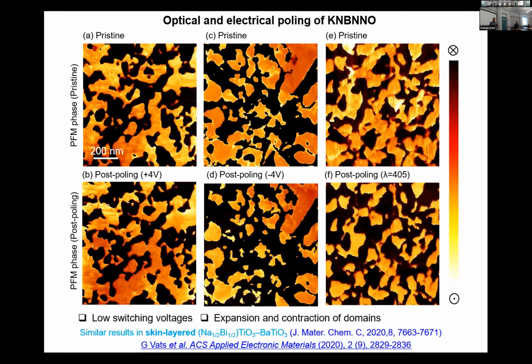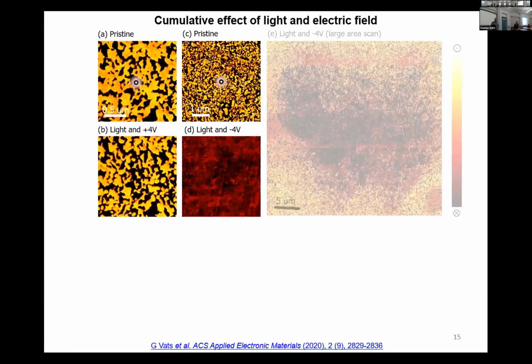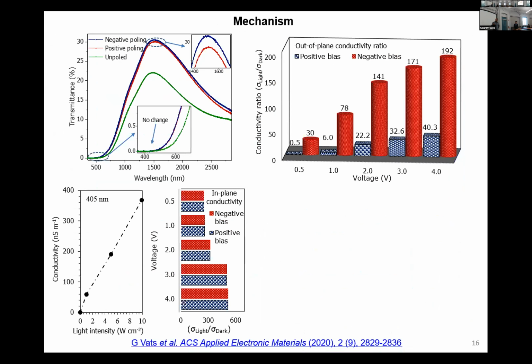I should quickly mention here that if you look at this particular figure, I only talked about this area where the absorption is maximum. But when we talk about photonic applications or completely optical applications, we don't want this. We don't want any absorption because that's loss. So if you look at this area now, it corresponds to this 1550 nanometer wavelength, which is actually used for telecommunication. So what you can do is you can change the state of polarization of the material, and you can modulate the incoming light. So basically, you can use it for wavelength division multiplexing, which we use in our optical fibers to communicate. That's another interesting point of this material, but we are working on that. Very interesting.